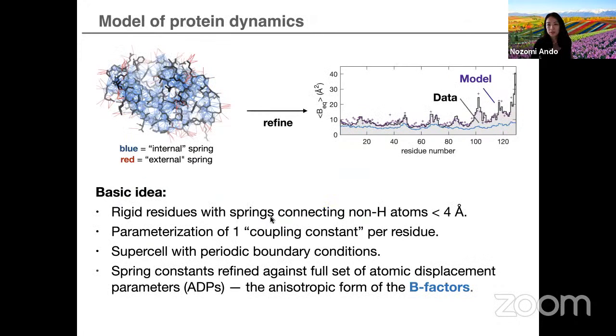And to answer this question, Steve did another simulation, this time of the internal dynamics of the protein. And again, he used an elastic network type of model, but this time internal contacts within the protein within a distance of 4 angstrom were treated as a spring. He also did some really clever parameterization so that there was only one parameter per residue. And again, he did a supercell simulation with periodic boundary conditions. And a key difference between this model and the lattice dynamics model is that this time he refined the spring constants to the B factors, not the diffuse scattering.